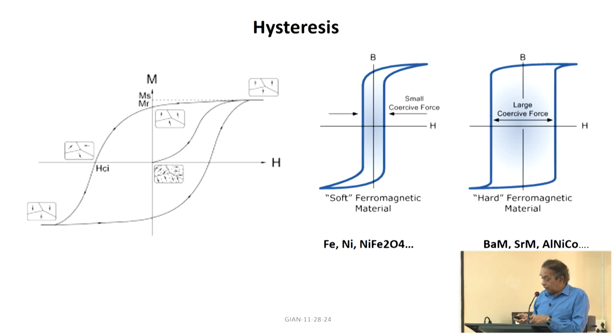And also there is domain rotation. So, now the whole domain magnetization will rotate and will try to align in the field direction. So, it is domain wall motion where the domains grow, and the domain rotation. These are the two mechanisms, and that is what really happens as you keep increasing the field. The magnetization increases until you reach saturation where all the domains are oriented in a particular direction, which is the direction of the field that is applied to it.